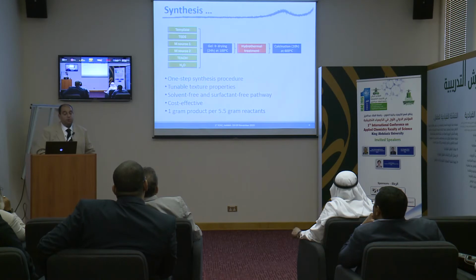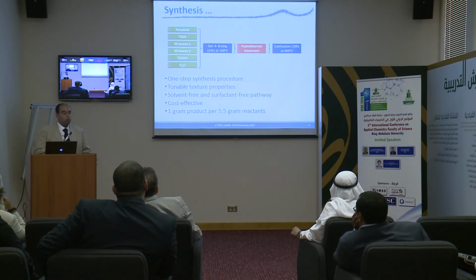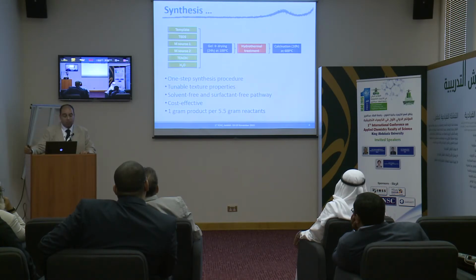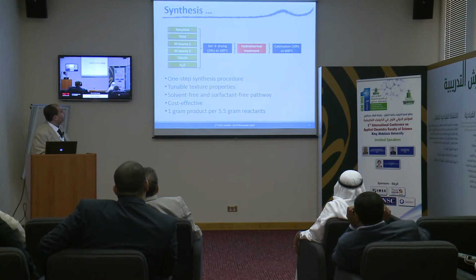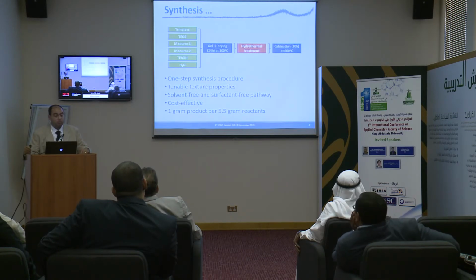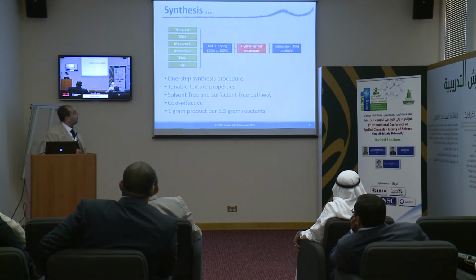The synthesis of the bifunctional catalyst, as I just said, you can really control your synthesis. So you add your template to your silica source. You will add two different metal sources, whatever they are, with a precise ratio, and you will adjust the pH with tetraethylammonium hydroxide, by adding some water, and the overall synthesis mixture is going to form a gel by aging for 24 hours and then drying for another 24 hours. Finally, a hydrothermal treatment step, and in the end, if you calcine your material at 600, you will get 1 gram of your catalyst out of 5.5 grams of your substrates.